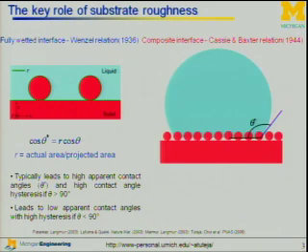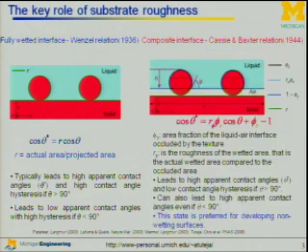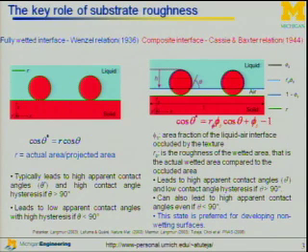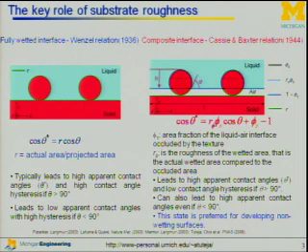The other relation is the Cassie-Baxter relation, which is a solid-liquid-vapor interface. As you can see, there is air trapped beneath these spheres. The equation is cosine theta star equals R_phi times phi_S cosine theta plus phi_S minus 1, where phi_S is the area fraction of the liquid-air interface occluded by the texture, and R_phi is the roughness of the wetted area — the actual wetted area compared to the occluded area. This state leads to high apparent contact angles and low contact angle hysteresis if Young's is greater than 90 degrees, and can also lead to high apparent contact angles even if Young's is less than 90 degrees. This state is preferred for developing non-wetting surfaces.